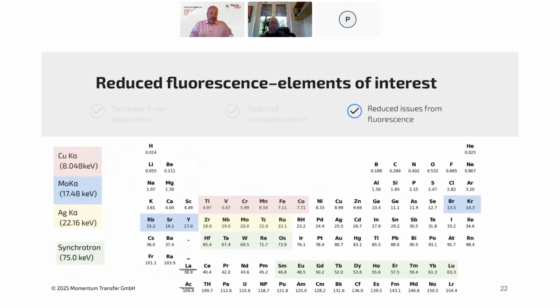There's another effect related to the energy, which is the effects of fluorescence from the sample. So fluorescence happens when your working energy is slightly higher than the energy required for the X-ray to knock an electron out of the atoms in your sample. So you have certain elements that are sort of problem elements depending on the characteristic energies that you're using. So unfortunately, while copper K alpha is typically the most commonly used in the lab, this is actually the most problematic for pretty important elements for a lot of minerals, which is titanium to cobalt, and particularly for manganese, iron, and cobalt. And so in those cases, oftentimes people will change their system to a cobalt radiation, which is slightly lower energy, and then you don't have problems from iron and cobalt.